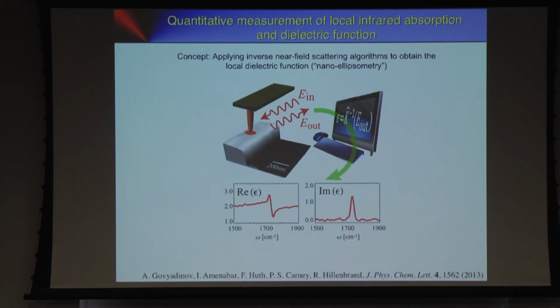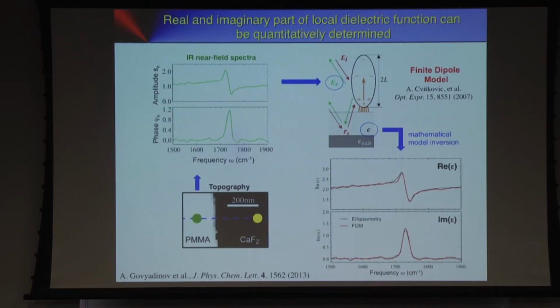So this is kind of in a fashion of nanoellipsometry. And this is how it works. We take the spectra, then we have a model here, and then we reconstruct. Actually, I don't have time to go into details, but the red spectrum here is the real and imaginary part of the dielectric function. In the background, we have ellipsometer data of this PMMA film. The point is, this is a heavily nonlinear problem. To invert that is rather tricky.